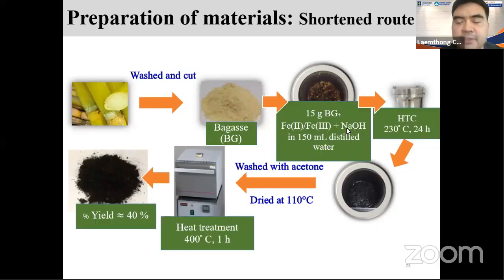When we talk about the sodium hydroxide, you might say, oh, why do you use sodium hydroxide in this case? You call it the cleaner way, but why do you still put the sodium hydroxide inside? Of course, we still use the sodium hydroxide, we still use the acetone, but in a lower amount. We use sodium hydroxide not for the activation, but just to precipitate the magnetic particles in our system. In this case we have iron 2 plus and 3 plus together